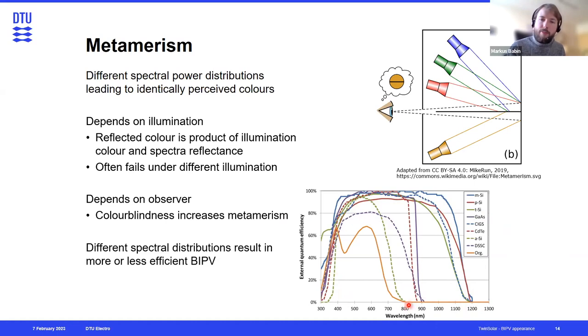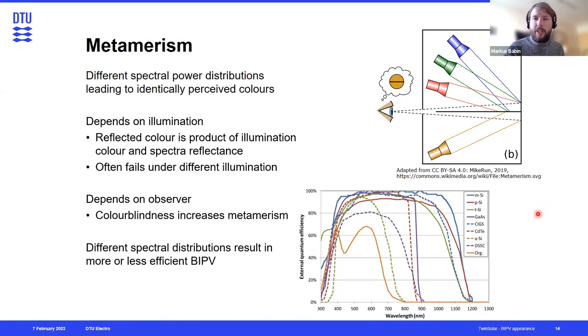This also applies to BIPV operation. Depending on how much of the spectrum is reflected from a BIPV surface, that will affect efficiency. Different PV technologies have different spectral responses or quantum efficiencies — some absorb more in the infrared, like silicon, versus most thin-film technologies which mostly absorb in the visible range. Therefore, tuning the color of a BIPV system has a large effect on both how we perceive it and how it affects BIPV performance.